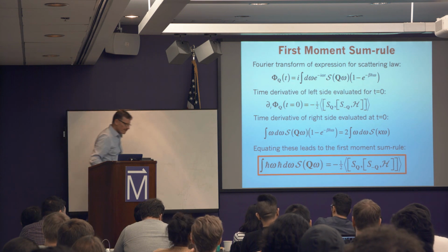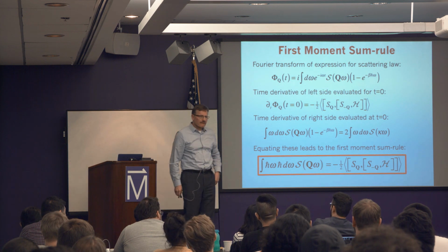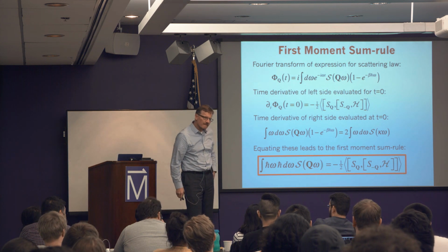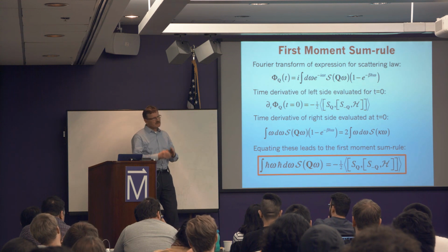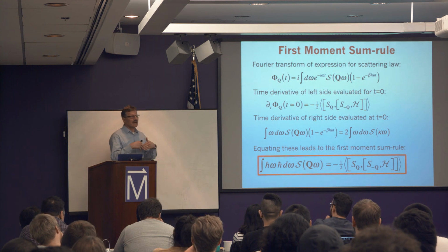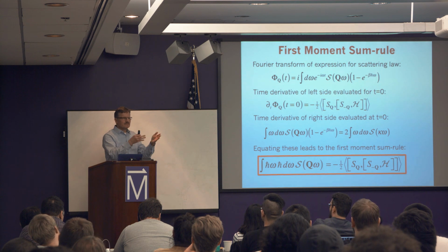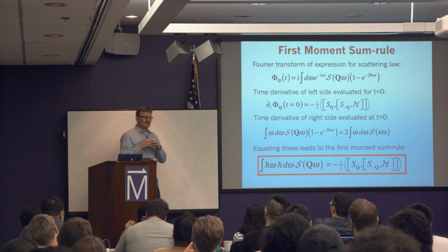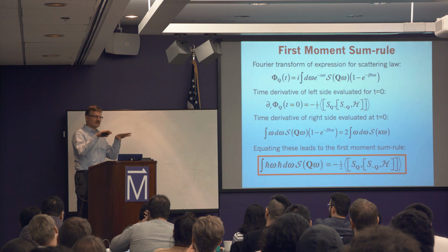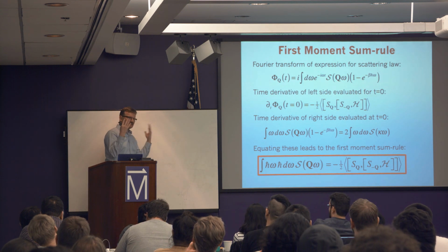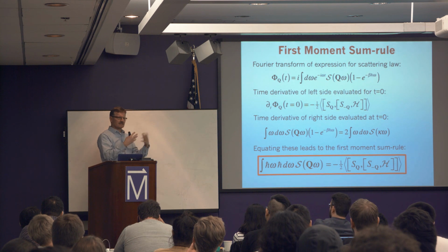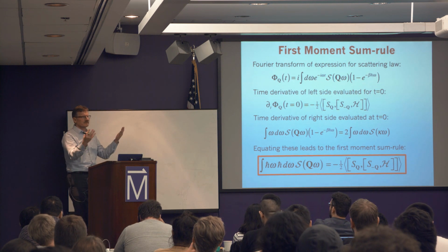Does it matter much if your magnetic moment comes from the spin or also the orbital moment, or does it just change the form factor? It basically just changes the form factor. You're as sensitive to the spin part as the orbital part. The form factor will be different for those two contributions. It's good to think that you really are just interacting through the dipole-dipole interaction. Whatever produces a dipole moment, you will detect it.